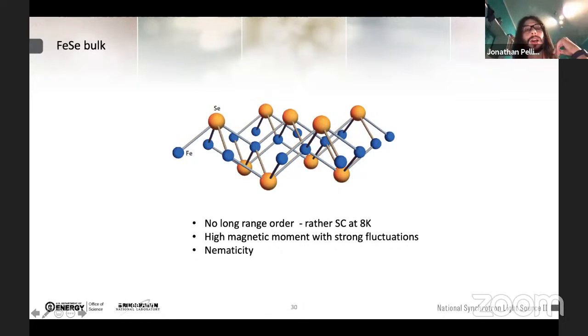Contrary to most of the stoichiometric compounds in the iron pnictides and chalcogenides, iron selenide doesn't have any long range magnetic order, but the ground state is superconductivity at 8 Kelvin. However, it presents a pretty high magnetic moment, which implies a strong magnetic fluctuation at higher temperatures, about 50 Kelvin. This material also has a nematic transition.